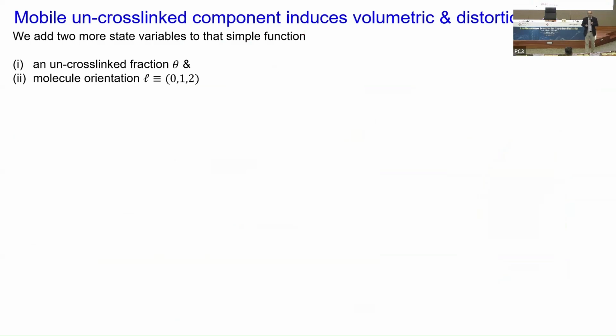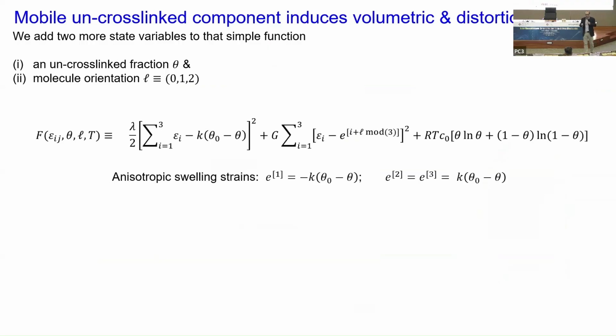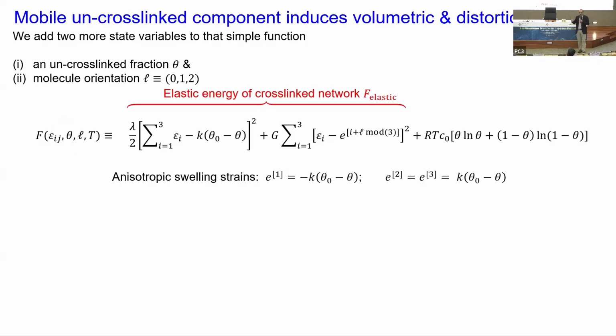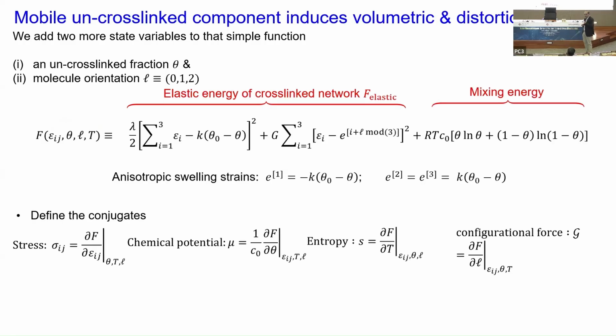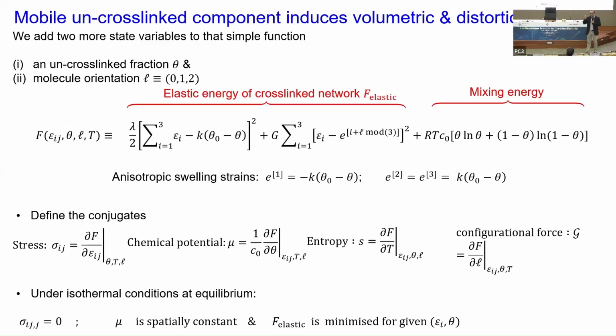Now, because I'm being told I have only 10 minutes left, I'm going to speed up a little bit. What I'm going to say is that you can develop a thermodynamic theory. And the thermodynamic theory means that now you've added one more state variable to the problem. In addition to strain, you've also added a concentration of this mobile species and the orientation of the mobile molecules. And you can now run the handle of developing this kind of a theory. You have an elastic energy, you have a distortional energy. And you can define all these conjugates, etc., and you can solve this problem.